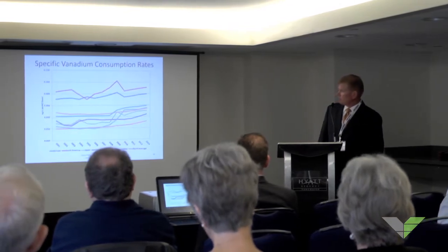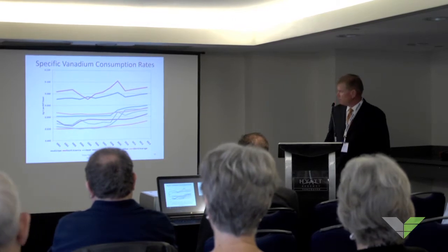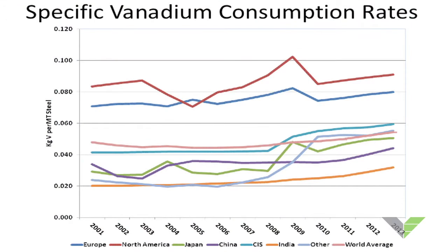Here's the data looking at specific consumption rates, and again, you see here the North American numbers on top, and you see India down here. The interesting line in this picture is these other countries where consumption has moved up rapidly, and then you see what's come here in China the last couple of years. Again, if you do the math, tons of steel produced in any one country times the specific consumption rate, that's going to tell you how much vanadium they're consuming. And because there's so much steel produced in China, what you see is the changes in the situation in China having a big impact.